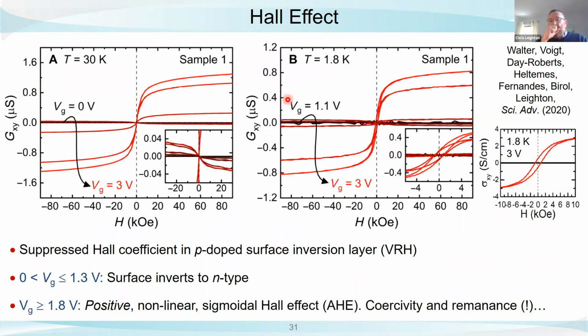magnetism? So we went to the Hall effect again. This is at 30 Kelvin, going from 0 volts to 3 volts. This is the Hall conductance plotted as a function of field. The starting state, that surface state, turns out to have very low mobility, so there's almost no Hall coefficient. And if you blow up what happens here at low voltages, you turn on a negative Hall coefficient.